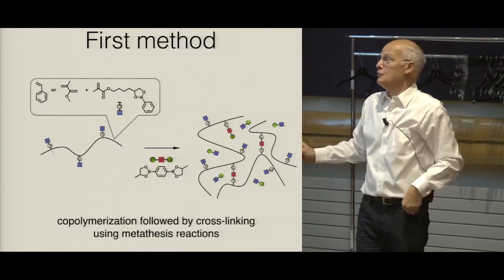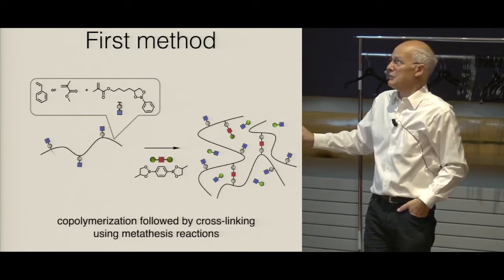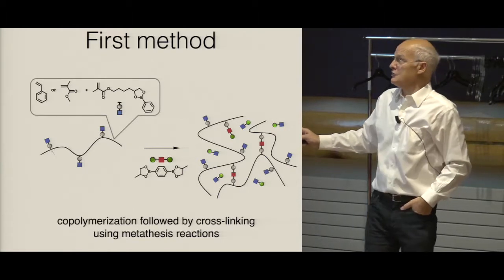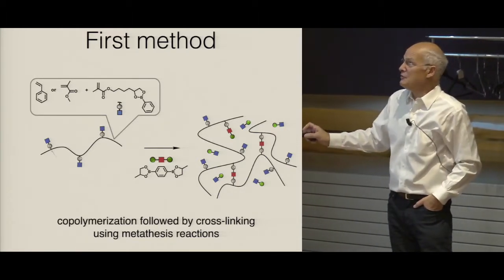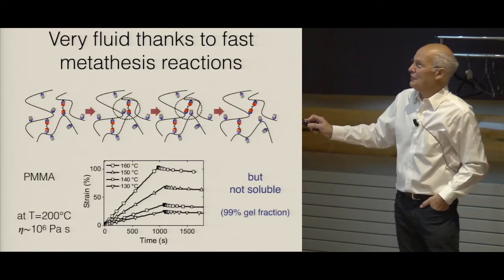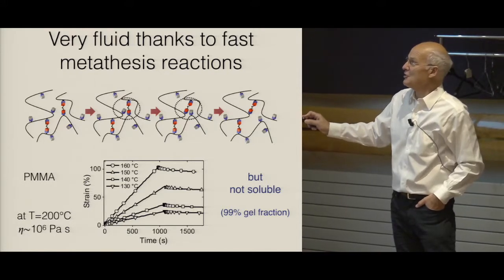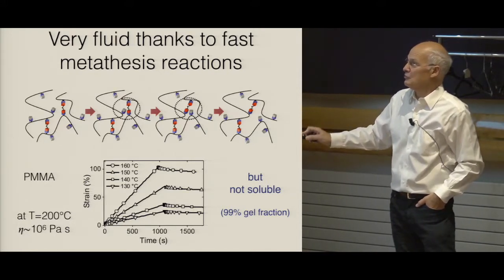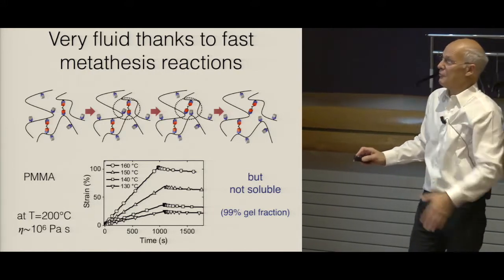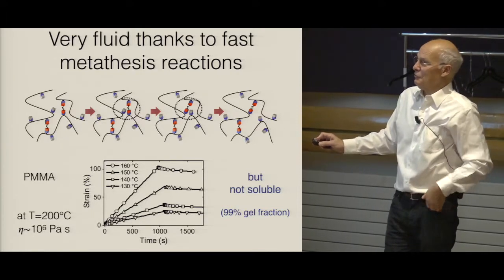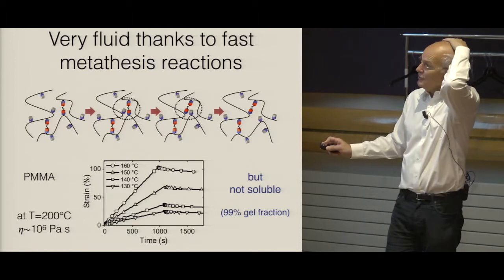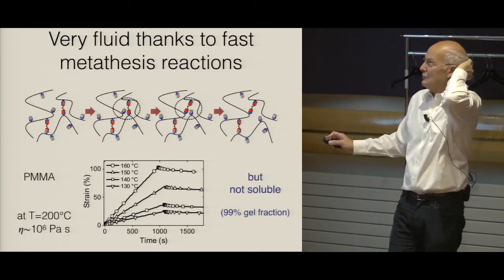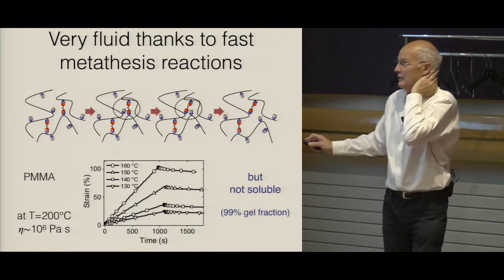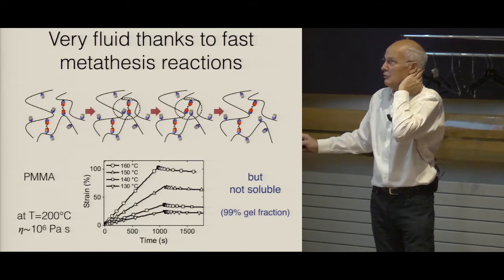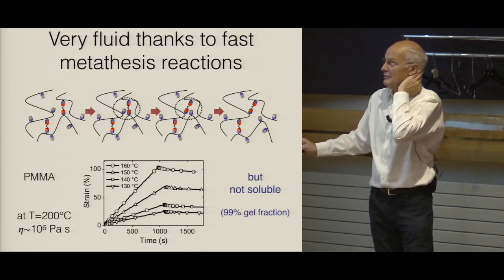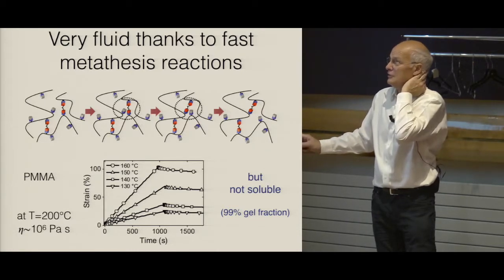And then we could, for instance, copolymerize monomers which have these boronic ester groups, and then we could cross-link them by this metathesis reaction. But at the same time, the metathesis reaction was giving, at high temperatures, these exchange reactions which enable the system to flow. And so, for instance, we made a plexiglass, a transparent polymer, with polymethyl methacrylate, for which we could adjust viscosity. It was completely cross-linked, so it was not soluble at all, but we could manage to have a very low viscosity at high temperature.